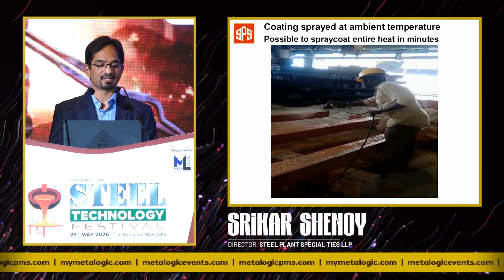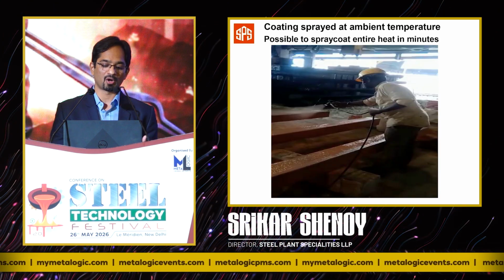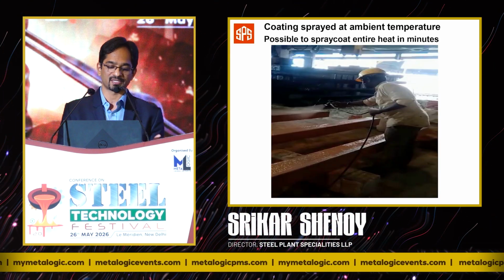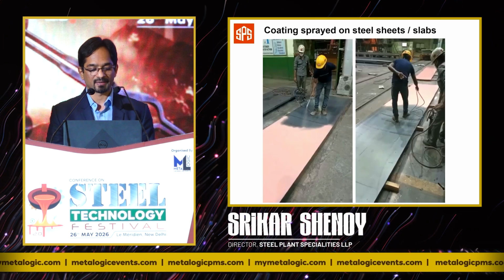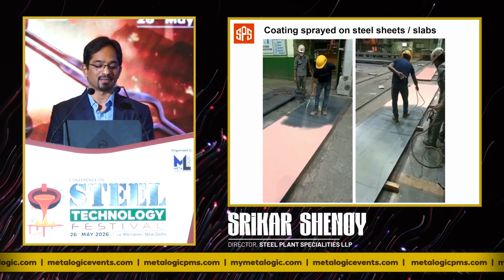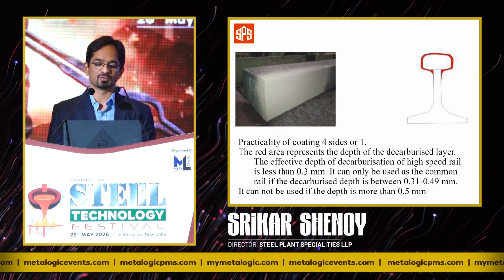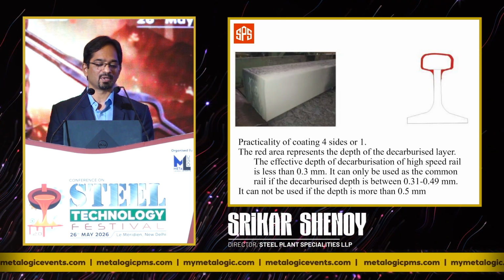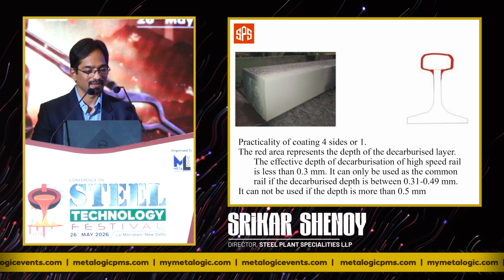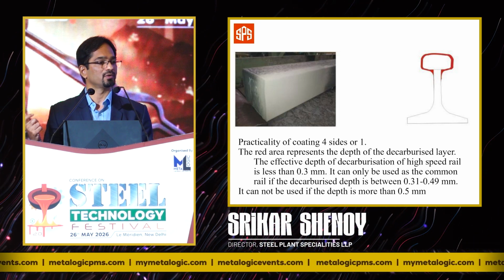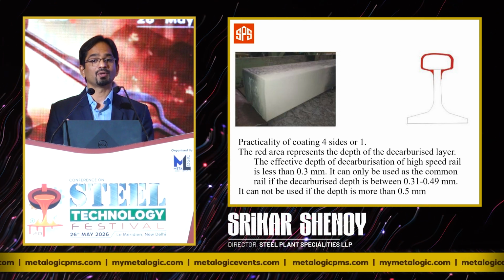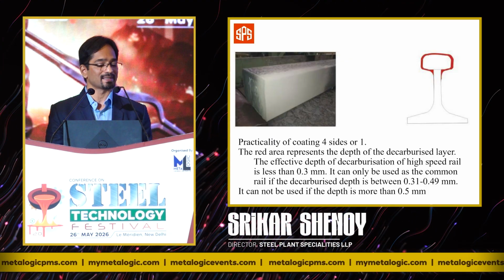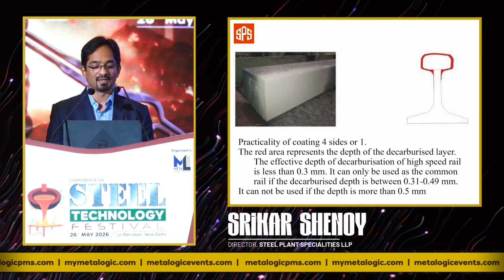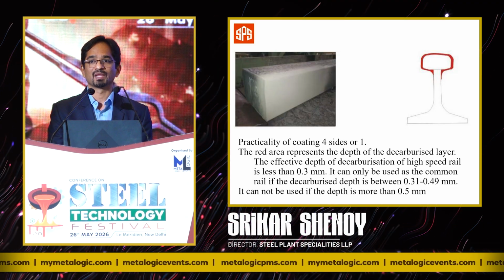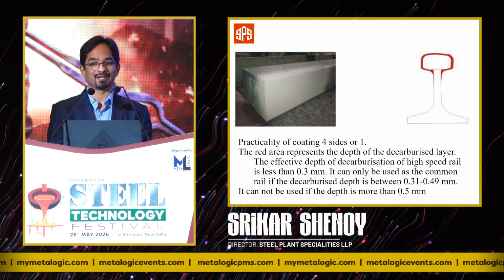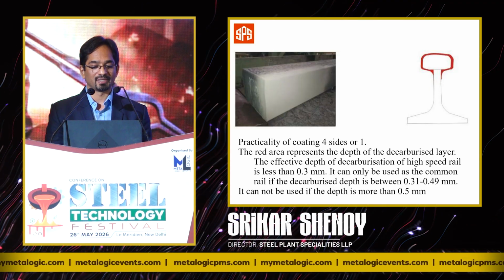Coating is sprayed on the billets prior to charging into the furnace, be it long products or flat products, as you're seeing. These are hot rolled sheets being spray coated prior to heat treatment, and at all stages to control scaling and decarb. A quick example of controlling decarb. What you're seeing on the screen is a billet which will be hot rolled to make rail steel. Controlling decarb on rail steel is most important simply because if you have decarb on such critical areas on which the train moves, it would lead to cracking and failure. And hence, you need to control decarb.